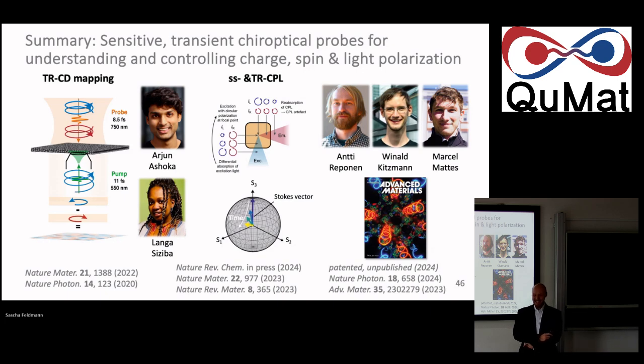Yeah, so you mentioned you were initially skeptical about the Rashba splitting, and I know you've been skeptical about that mainly because of the high recombination in the perovskites. Can you comment on that? Yeah, so I'm still skeptical, especially about big claims on, say, large Rashba splittings, and I think most have been debunked. There were some nice-looking ARPES works that have been shown to be not real. So I think it's not a big number, and funny enough, from the speed of motion of our spin packets, we can actually do a back-of-the-envelope calculation on the suggested Rashba splitting that would dictate such a movement. And actually, that is in line with rather pessimistic small Rashba splitting values. But it's also nice to know that it's in line with that and not with big claims. So if it's there, it's small.